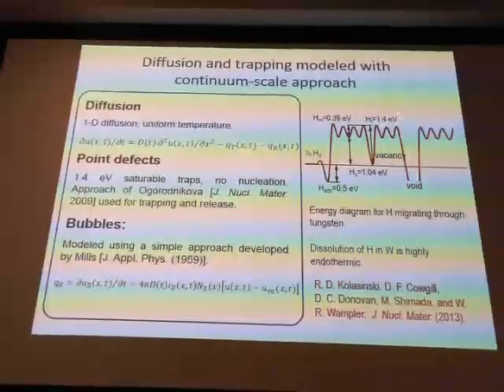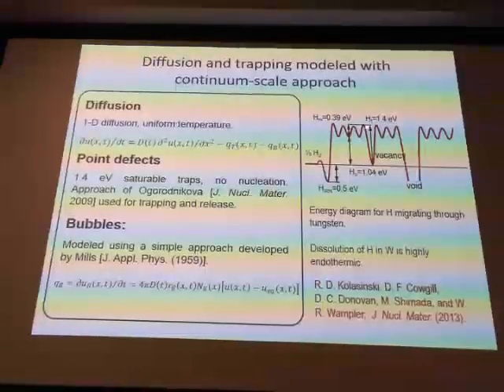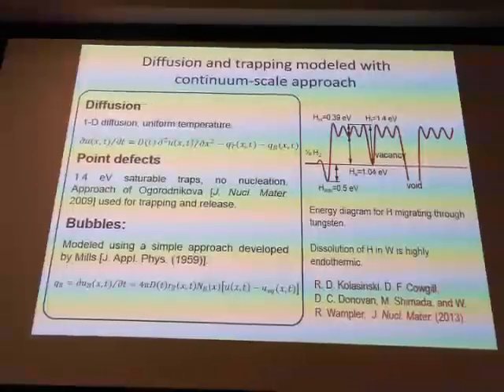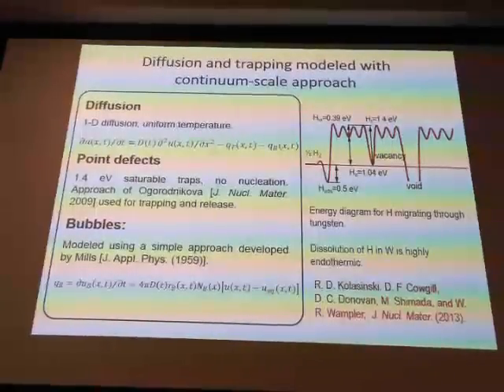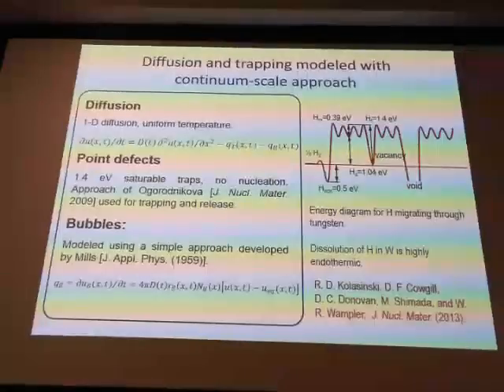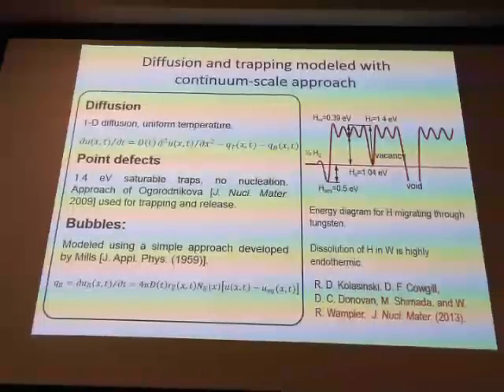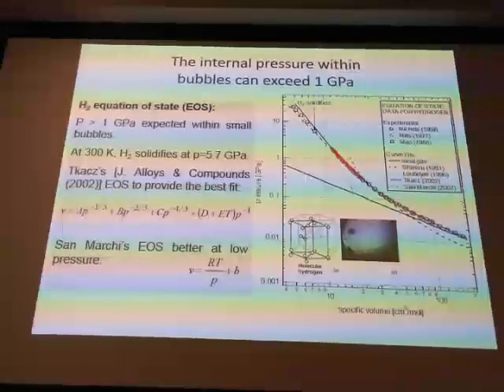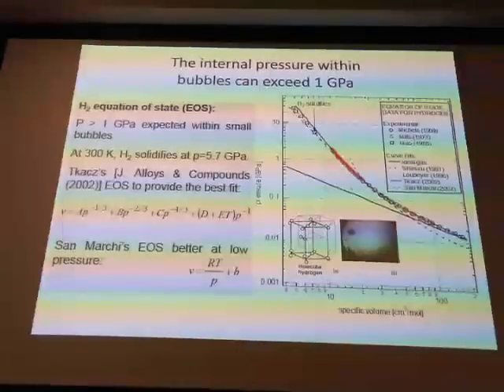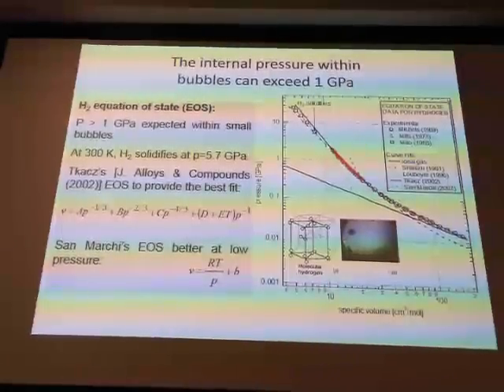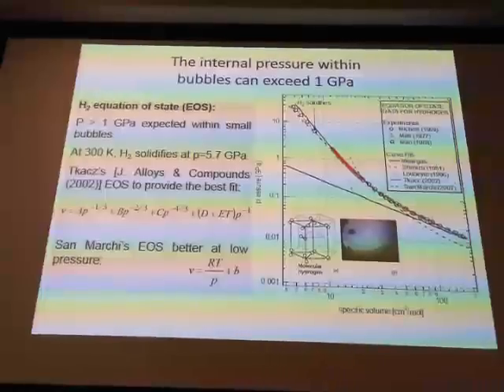Vacancies in tungsten have been measured to have an energy relative to the migration energy of about 1.4 eV or so. When it encounters a void, that's an extremely stable state. It recombines into molecular hydrogen and stays in there. And it's extremely hard to get out. So much so that you can actually get in excess of gigapascals of hydrogen in these near-surface bubbles.